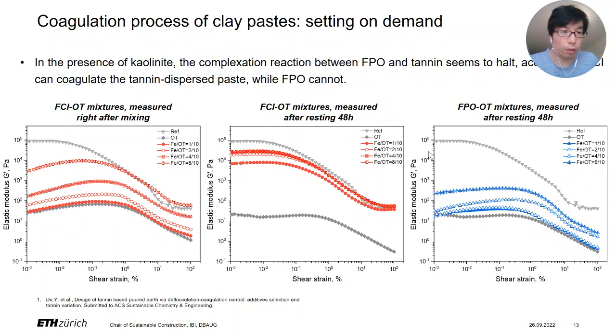The interesting thing is the phosphate. Even after resting for 48 hours, the paste is still liquid-like. Yes, we saw some precipitate form in the solution, but not fully. With these 2 days, they are not sufficient, or they are not strong enough. The affinity of the phosphate is not strong enough to remove all the dispersing effect of the tannin, even with the higher addition. And we also tested continuous shearing, but it didn't help to remove this dispersant effect of the tannin.